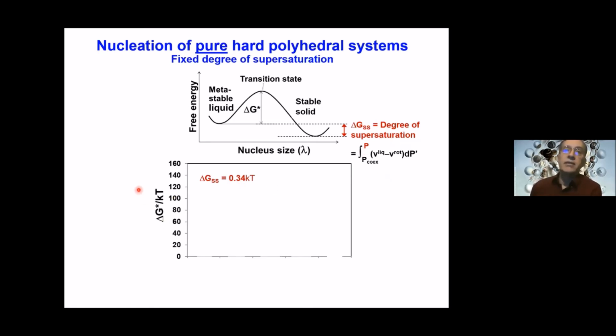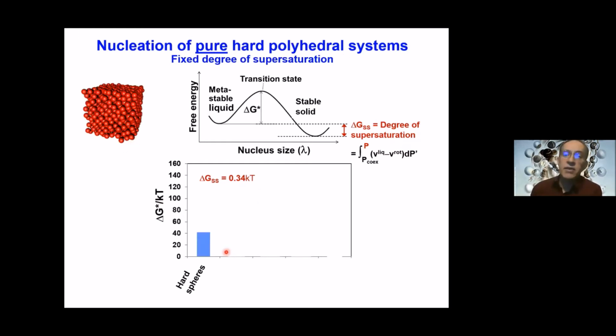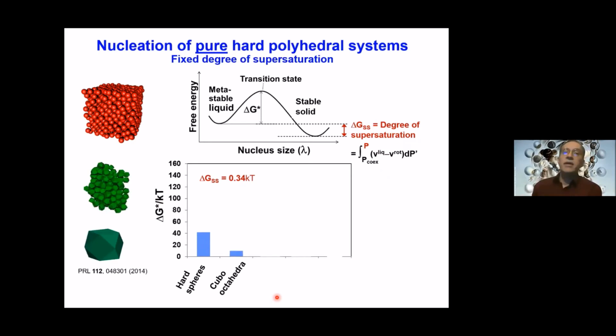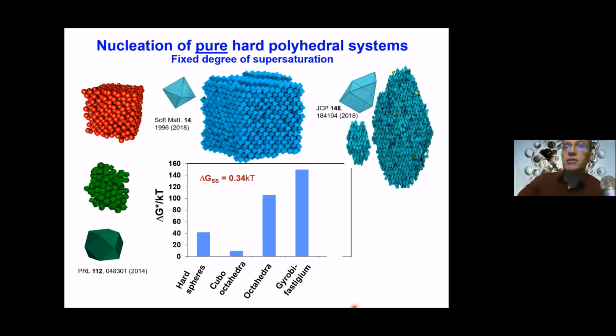So let me show you just some sample results for a fixed value of this supersaturation, and we can take hard spheres as a reference. For these conditions, hard spheres will have a relatively large barrier, so the assembly will be somewhat slow. And we find that there are some pure polyhedra, these are all hard, that can actually assemble much faster, so they have faster kinetics, and there will be some other shapes that actually have much larger barriers, so will be much slower kinetics.